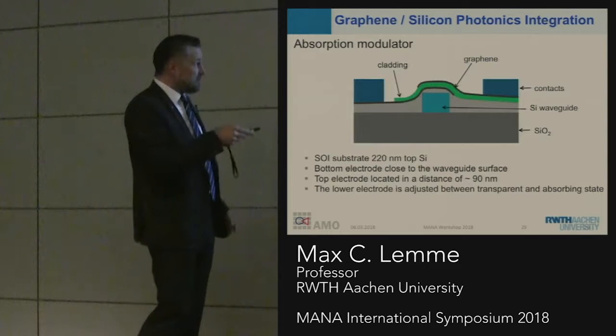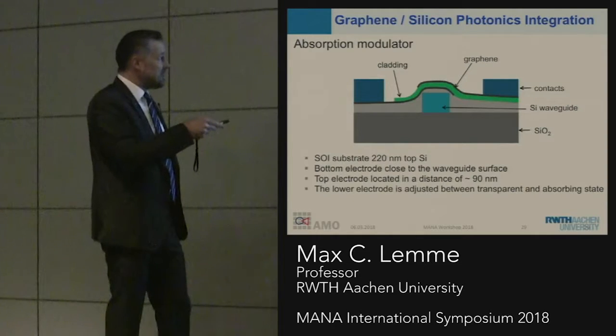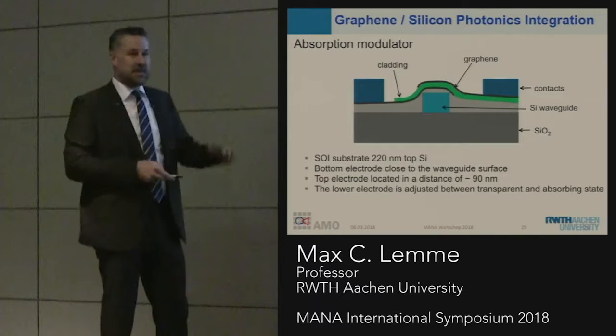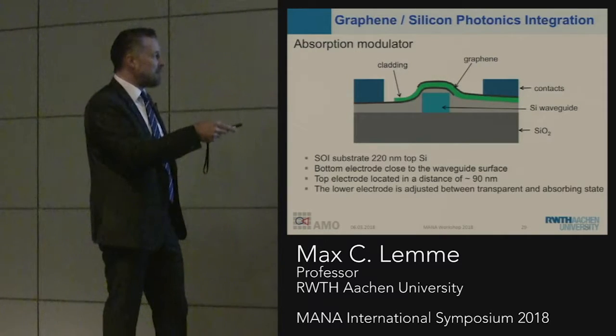So the device we made was the following. We had a silicon waveguide. We had this absorption layer here of graphene in black, and we had a second graphene layer to gate the first one. So we can apply a bias here.